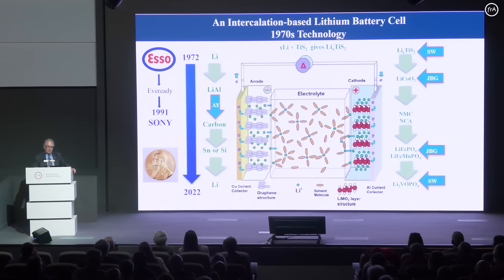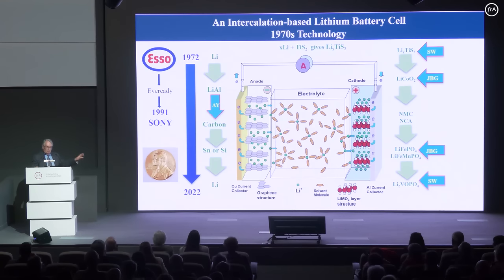About 20 years ago, John Goodenough also found that these lithium iron phosphates, what we call LFPs, you could take the lithium in and out of the host structure with no issues. They work very well, and there were some folks at MIT, Yet-Ming Chiang, who actually commercialized that material and showed it could be a useful battery. But it has a very low energy density, and I'll show you that in a minute. So we've been working on how we can increase it and make it better.